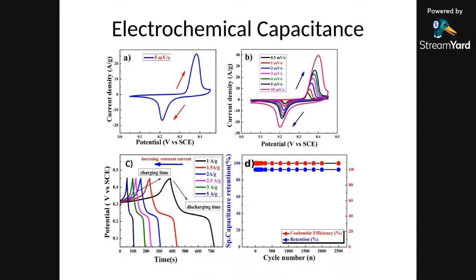We did this test in aqueous KOH electrolyte, and you can see the cyclic voltammetry here, and this is the nature of the CV. If it's a pure capacitor, it will be rectangular. If it's an intermediate or pseudocapacitor kind, you get a distorted rectangle. But what you are seeing is completely a peak. Charge peak and discharge peak show a completely intercalative nature of behavior, and that was very, very surprising for us.